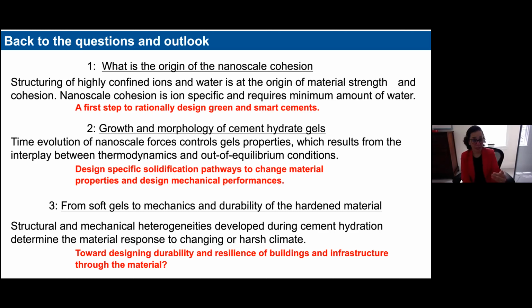From this information, we can build a new approach at a more mesoscale level to rationalize what happens as the nanoparticles start to gel, and how the development of the microstructure of the gel determines the porosity and the mechanical strength of the material, and how this development allows us to identify new pathways to change material properties and design mechanical performances during cement hydration.